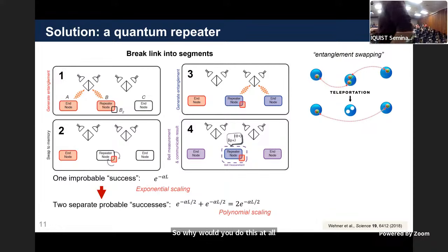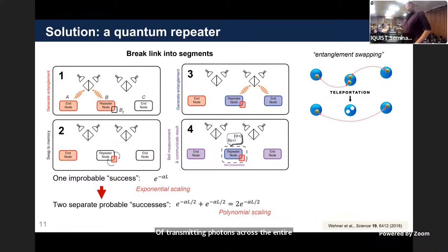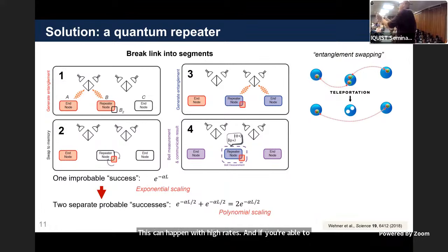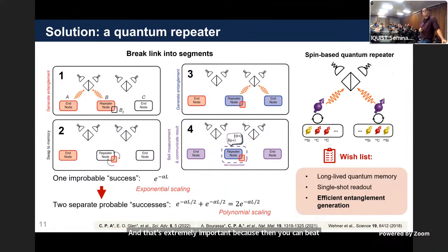Basically, the reason that you would do this is you turn one highly improbable success of transmitting photons across the entire link length into two statistically separated, probabilistically independent processes that are much more likely. So if there's no significant loss between A and B, and these nodes are very, very close, this can happen with high rates. And if you're able to do the swapping, you can basically trade the entire link loss for two more probable events to happen. And so you can turn from something like an exponential scaling to something that looks more polynomial. And that's extremely important because then you can beat this 10 to the 77 number of loss.